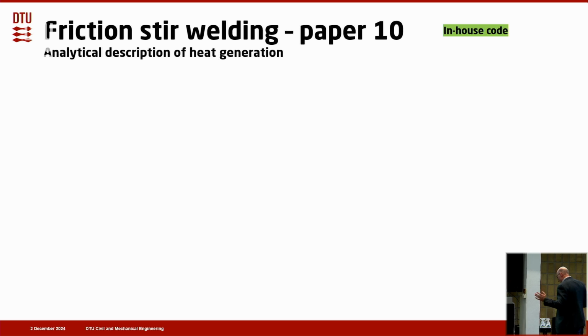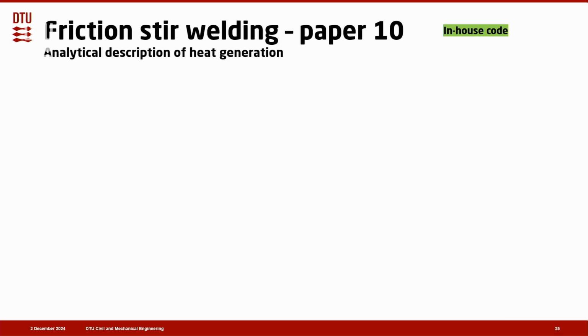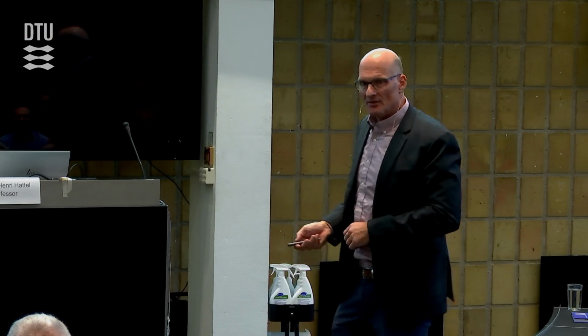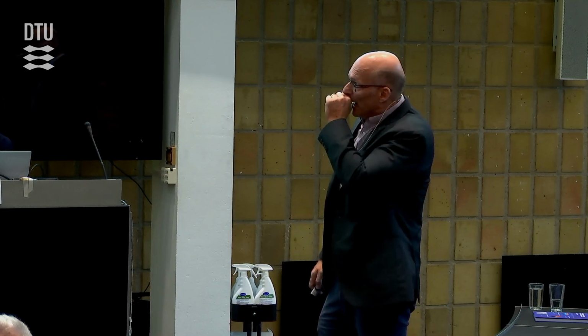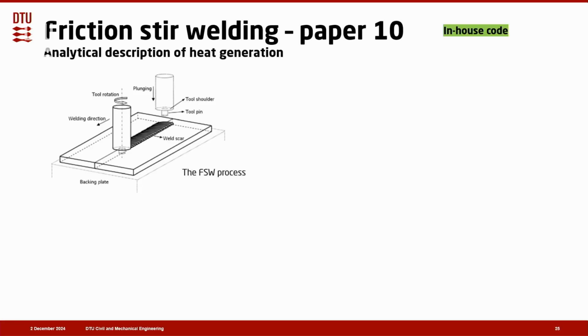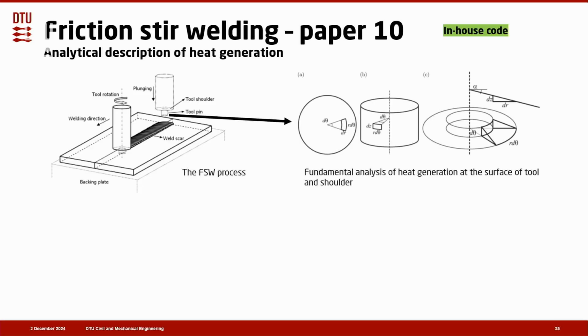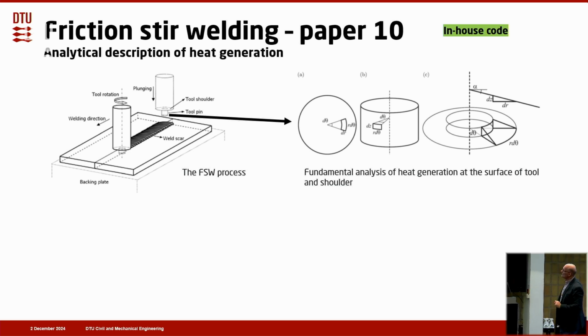Now we come to friction stir welding. That was this process where you have a rotating tool. It's a mechanical welding process, and then you weld the two parts together. And here you have an indication of the friction stir welding process. We did a very fundamental analysis of the heat generation at the surface of the tool and the shoulder. Nobody did that in literature before at the time.